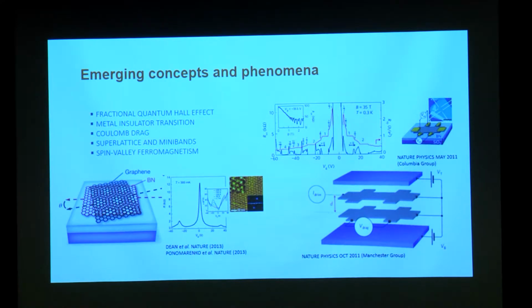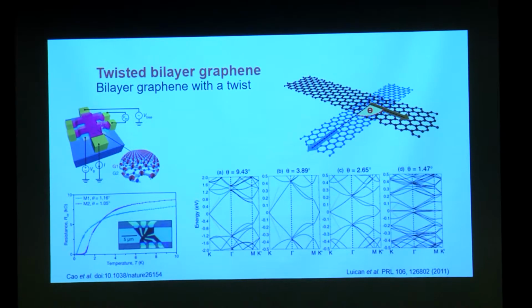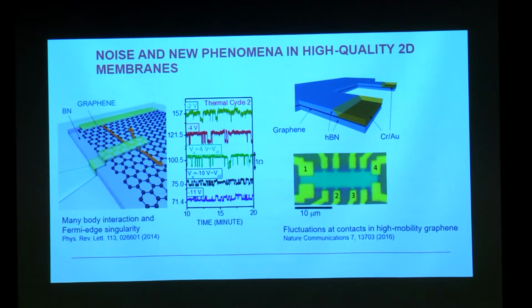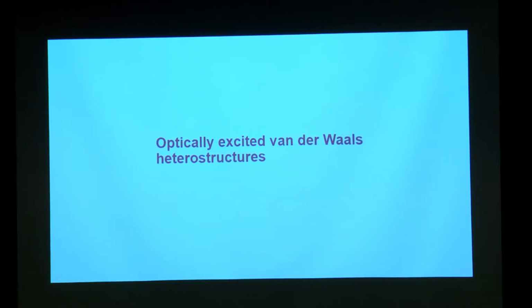And recently, of course, not just by heterostructuring, but also by using layers at slightly different angles, one can go to superconductivity. This has been one of the major discoveries in the last year or so, where by taking two graphene layers at an angle of 1.12 degrees, you can hybridize the layers in such a way that the hybrid becomes a superconductor at sufficiently low temperature. All right. But today's talk is about optically excited van der Waals heterostructures.